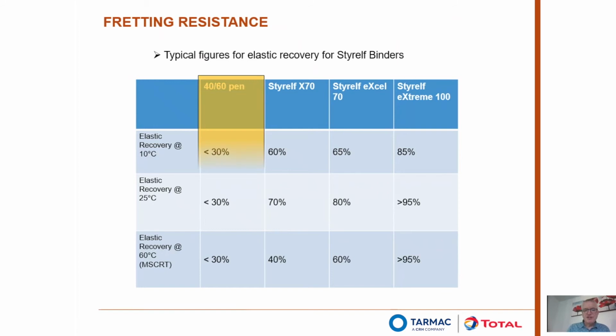So if you look at a 40/60 pen, for example, normal penetration grade bitumen, you can see that at 10 degrees C elastic recovery, 25 degrees C elastic recovery, and 60 degrees C elastic recovery, not great. You know, it's not really contributing anything towards elastic recovery. So it's all about the capacity of the bitumen to hold itself. Yeah, and once it goes past that point, it's going to flip out.